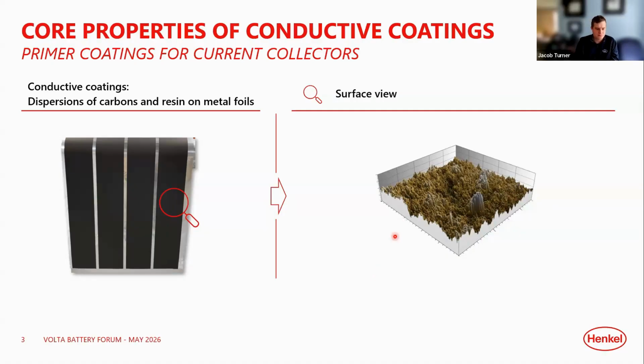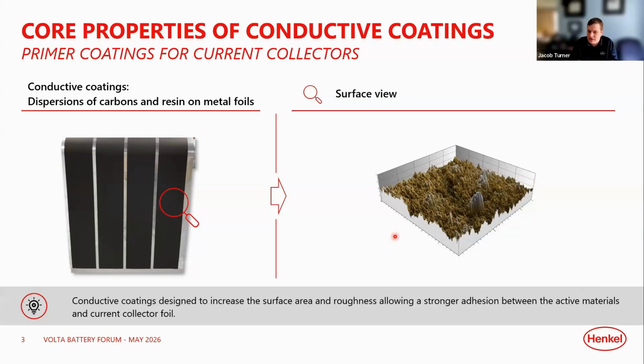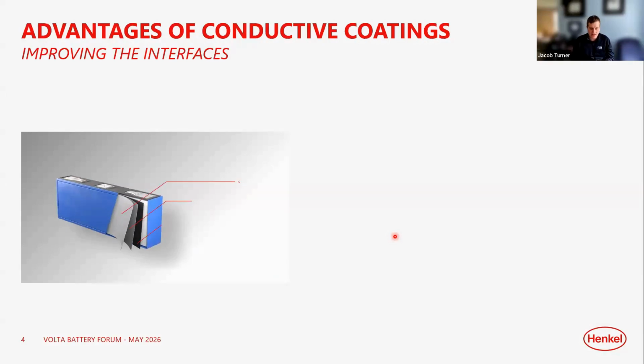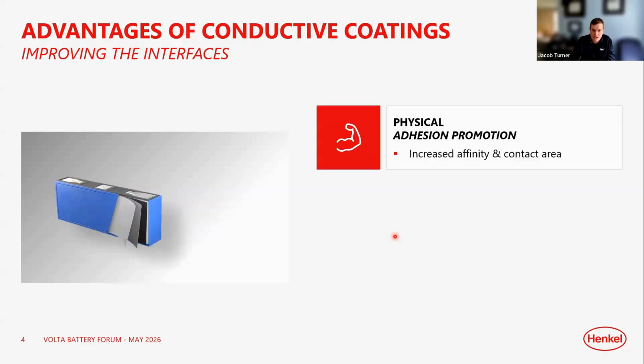And with that, the conductive coatings are designed to increase the surface area and roughness. It allows for stronger adhesion between active materials and current collector foils. We'll talk about the resulting impacts of this relationship. If you peel back the layers, we're taking this electrode, and I'll use that without referring in particular to cathodes or anodes, as these materials can be used on both sides, but turning it into a slightly more layered structure, with our conductive coating in the middle of the sandwich, where we're adhering to the underlying current collector and also that of the active material. So it's very important for us to adhere strongly to both of these materials and have the appropriate interface formed with both materials to facilitate improved electron transport across the electrode.